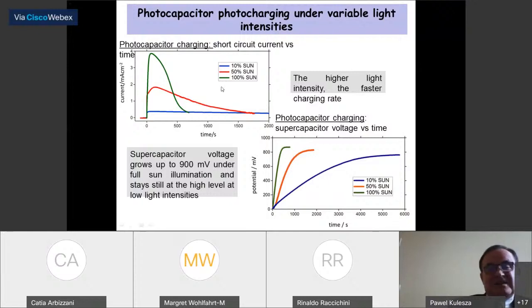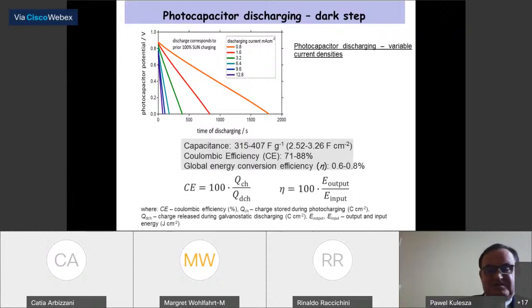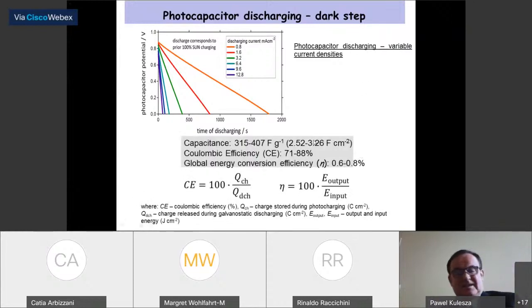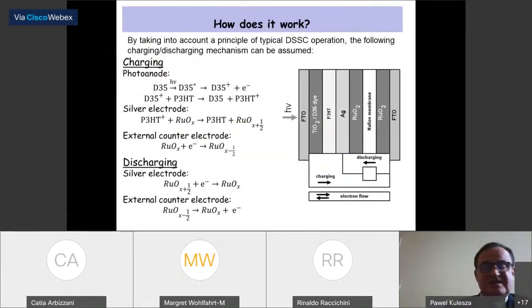And indeed, depending on the light you can charge, you can also observe change of the potential. Obviously, better light, better sun, like in Camerino in summer, would work great. And of course, discharging depends on how much time you need and what current you use for discharging. Briefly speaking, the Coulombic efficiency was at the level of 70%. Please remember, it is an electronic type device. Everything is a single system. Use of silver is not optimized, but it's interesting.